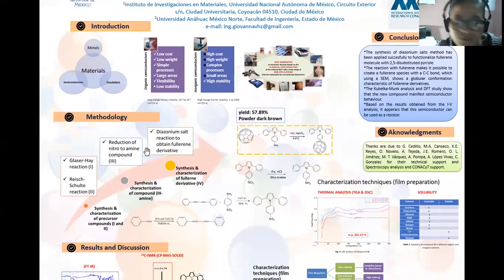In the methodology, the synthesis of the new compound is divided into 3 different stages: the synthesis of the precursors and the reaction in which the diazonium salts are involved to functionalize the pyrrole with fullerene. Finally, we obtain a dark brown powder, and the yield of this compound was 57.89%.